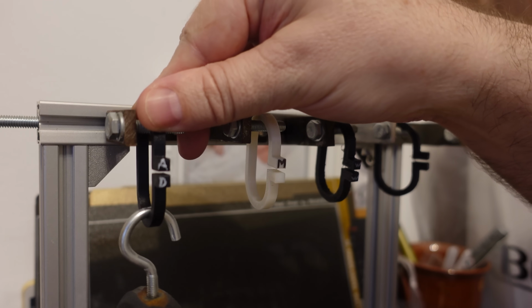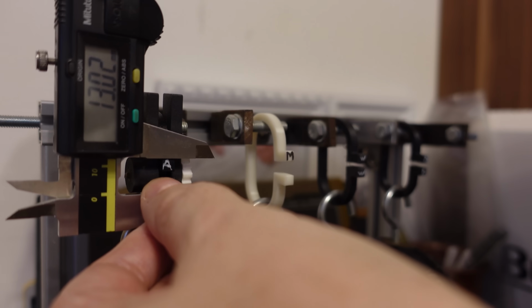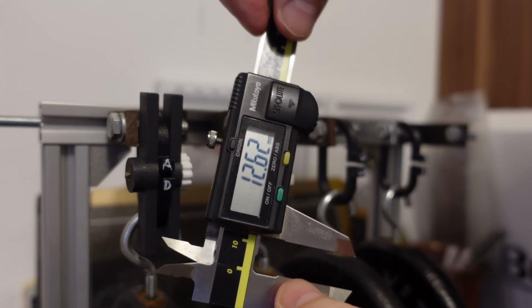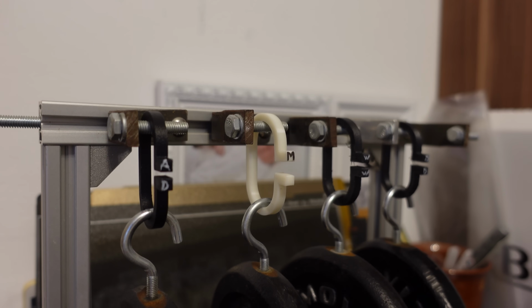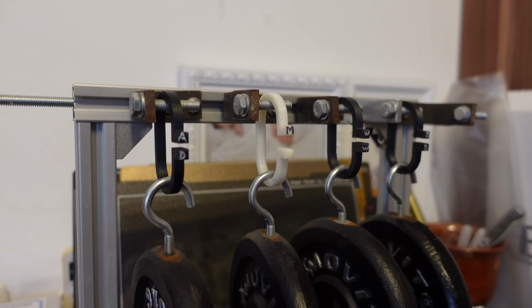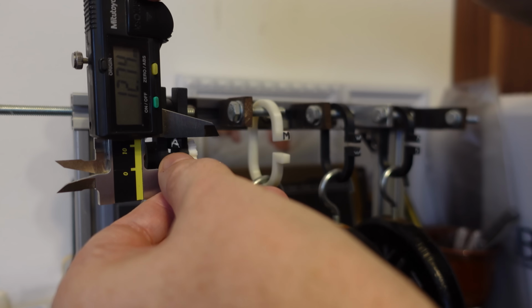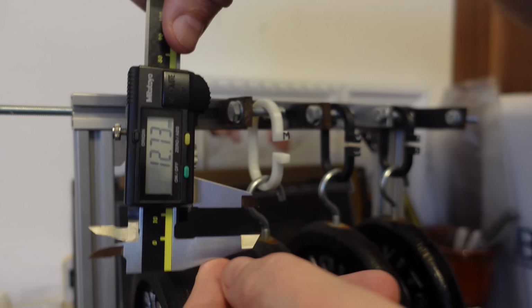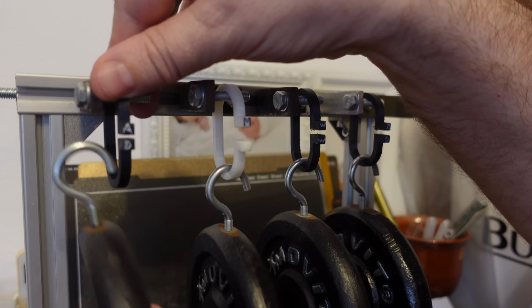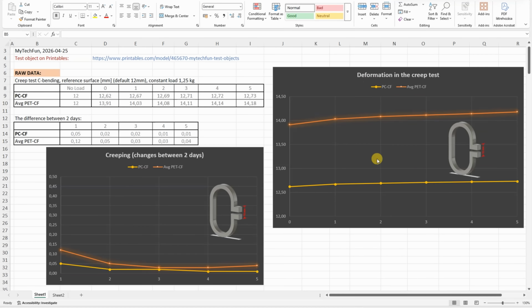Creep test, the deformation under a constant load of 1.25 kilograms. 12.62. So this is the initial deformation, and now let's jump 5 days. Day 5, the last measuring. 12.73. Let's remove the load. On this graph we can see the distance between 2 reference surfaces, and we can see significantly smaller deformation on this AddNorth PCCF compared to the average PET-CF. Creeping is the difference between 2 days, and that's presented here. In both cases this creeping is very minimal, but of course smaller on this PCCF.